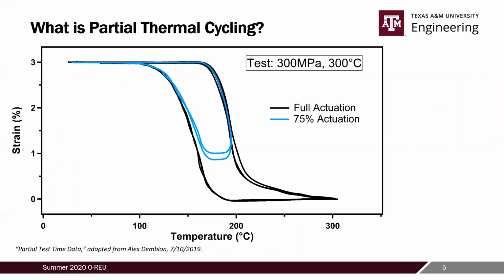Partial cycling is different from full thermal cycling because the material is not fully transformed between the austenite and martensite phases. Here we can see a full thermal cycle that goes all the way from one phase to another and back, and a partial cycle that only undergoes part of that transformation. So by doing less of a transformation in each cycle, we're able to increase the total number of cycles that we can get out of the material and ultimately extend that fatigue life.